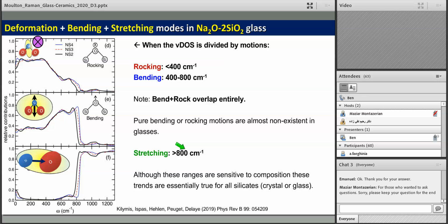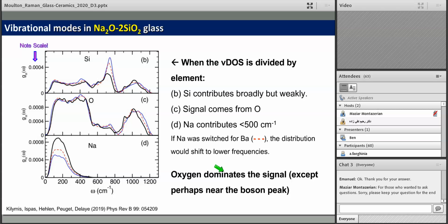So these stretching motions, where we saw those Qn bands a moment ago, don't have any mixing, so there's less ambiguity about the origin of these frequencies, but they basically dominate at higher wave numbers. These generalities are true for crystals and glasses, so you can apply them to almost anything. Just remember that if you're changing the mass, you will shift these frequencies. If we break the simulations of the vibrational modes down, instead of by motion or oxygen, by element, we have the graph produced on the left here. On the top is silicon, oxygen, sodium, and I invite you to note the scale here. This goes to 0.4. 0.4 is down here quite low in both of the bottom two panels for oxygen and sodium. So what's important here is that silicon motions contribute across the spectrum, but in low intensity.